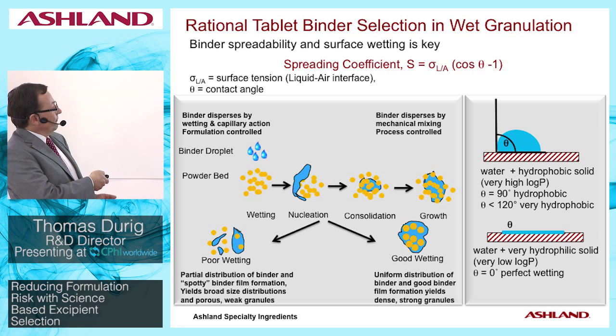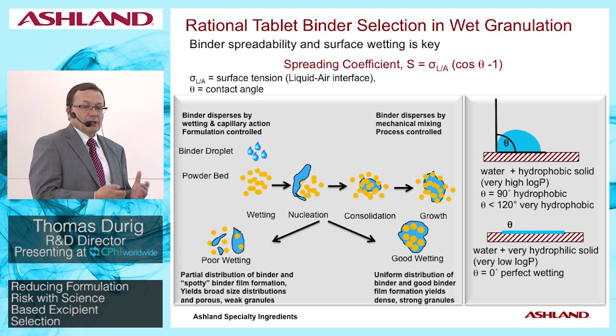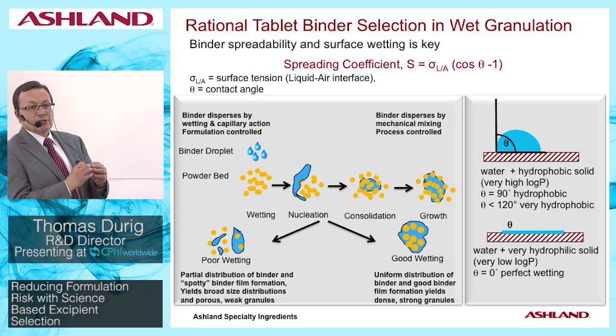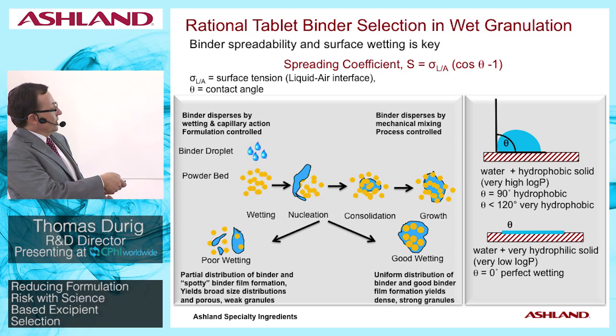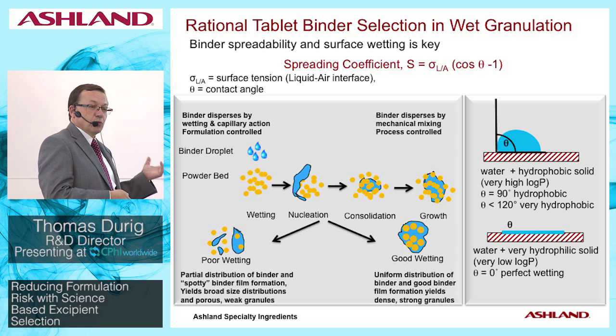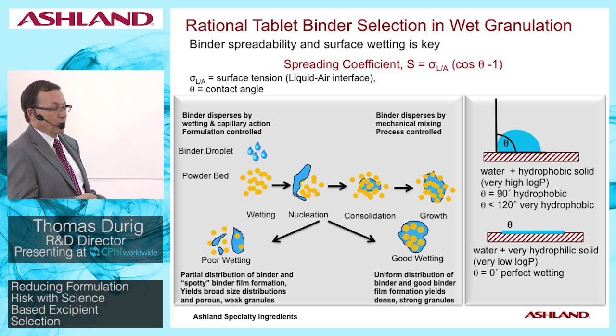And if this binder solution, on the other hand, has relatively poor wettability, one tends to get this scenario here where the contact angle is very large. The binder solution is really not able to spread very well over the powder bed as such, resulting usually in more inhomogeneous and poor binder distribution, weaker and more porous granules.